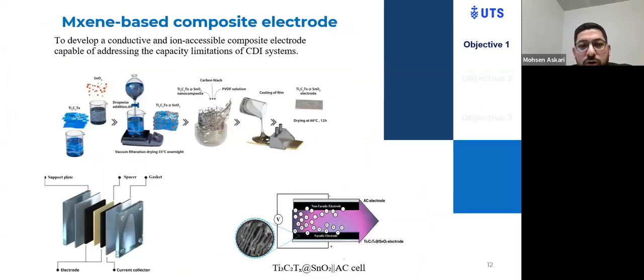The MXene-SnO2 composite and electrode were prepared, and the HCDI cell of the MXene-SnO2 AC cell was assembled. This SEM shows how SnO2 is anchored on top of the layer and between the layers and helps prevent the restacking of the lamellar structure of the MXene, and FTIR, XRD, and XPS show the successful preparation of this composite.